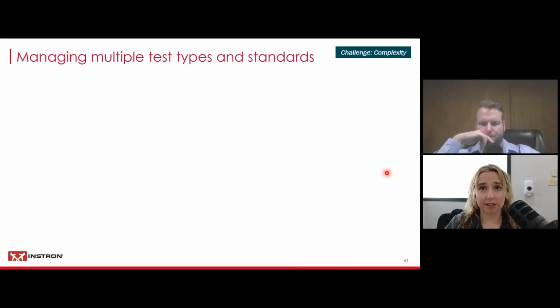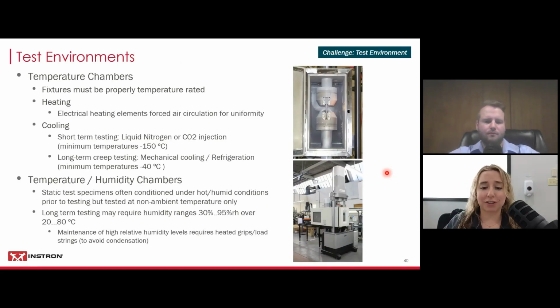When it comes to humidity testing, if you could go back just one, Stefan, thank you. As Stefan said earlier, specimens are commonly conditioned prior to testing under humidity, but they might take a long time to come to equilibrium. And so testing can typically be safely done at non-ambient temperature only. In some cases, humidity may be required for long-term creep or fatigue testing, which again, we recommend looking at humidity systems with third parties. Instron does not offer any kind of long-term humidity systems.